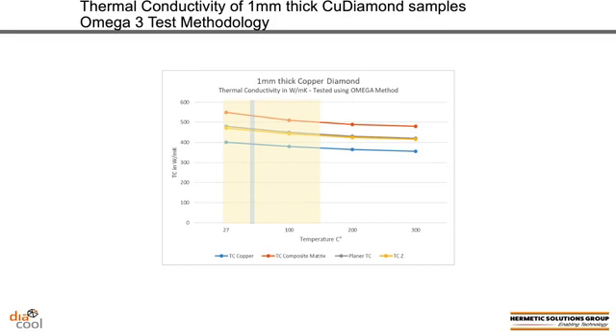That blue bar that you see at the bottom essentially takes the copper skin that's on both sides of this material and tests that skin by itself. And you can see it behaves very much like copper should. At room temperature, the thermal conductivity is around 400 watt per meter K.